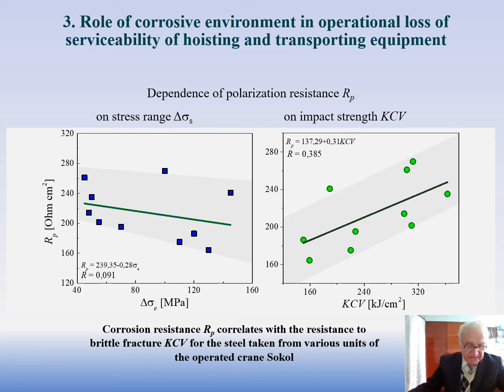Impact toughness is used as an indicator of its operational degradation, and polarization resistance is a measure of its corrosivity. Despite a significant scatter of the experimental data, a trend to the corrosion resistance loss with the drop of resistance to brittle fracture is quite evident. A high corrosion rate of the metal in the marine environment with hydrogenation capability implies the intensification of degradation process, especially in rolled steel susceptibility to hydrogen embrittlement. Based on this, it is suggested using such a relationship for elaborating a non-destructive method to assess the current metal state.